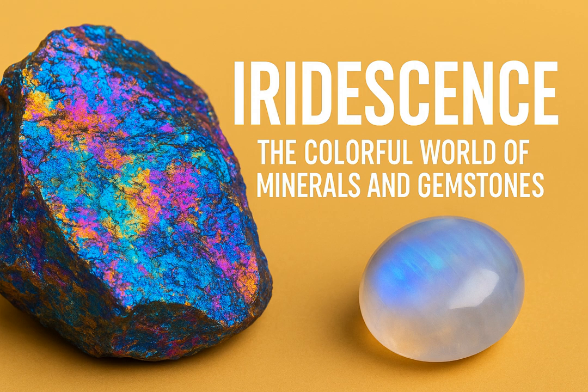So iridescence is often reflection or diffraction from layers or surfaces, while pleochroism is about absorption through the crystal structure. That's a great way to put it, yes. And unlike iridescence, which you can see easily with the naked eye just by moving the light or the stone, pleochroism, while often visible, is typically enhanced and more clearly observed with specialized tools. Like what? Like polarized light or a dichroscope, which isolates light vibrating in different directions. Although you're right, for many strongly pleochroic gems, you can absolutely see the color change just by rotating the stone in your hand. Can you give some examples? Sure, classic examples really highlight this distinct effect. Take tourmaline.